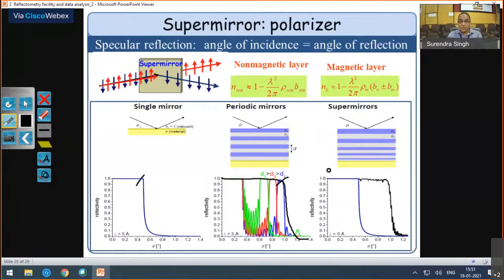So you will have, suppose this is your reflectivity plot, spin up reflectivity extending up to here, and spin down reflectivity only up to here. So in this region, plotted as theta versus reflectivity, you have only spin-up neutrons, and this theta depends on the wavelength.